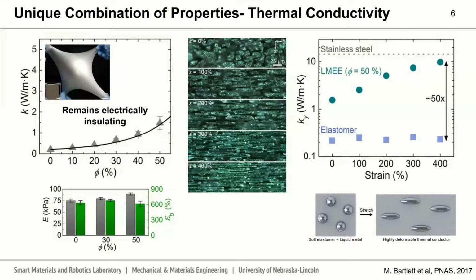This increase in thermal conductivity actually begins to approach some rigid metals, such as stainless steel, and this is ultimately a 50x increase over the original host elastomer composite that is strained up to 400%. So it's a pretty unique combination of properties. This material is soft and rubbery, but then exhibits some properties only really seen in rigid metals, such as very high thermal conductivity approaching 10 watts per meter Kelvin.